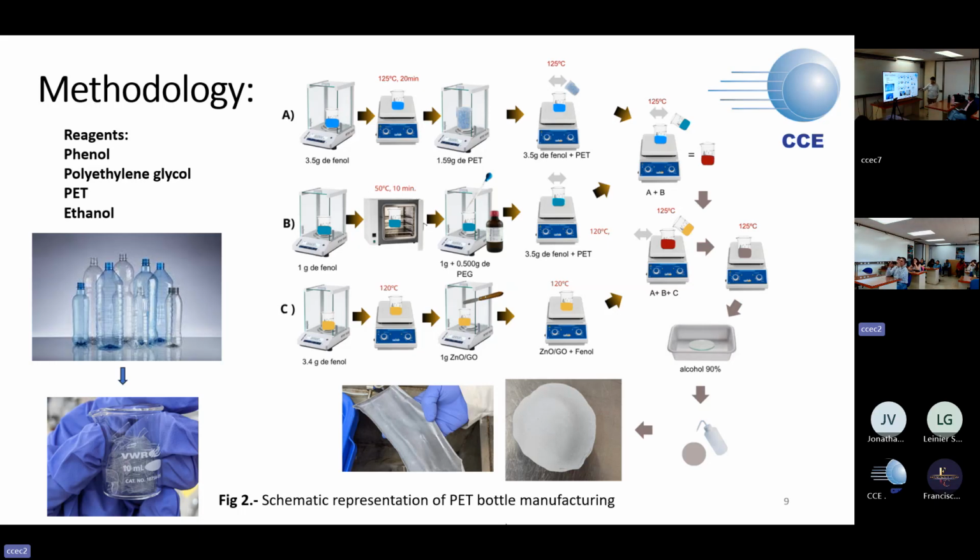In this vessel, we introduce a glass like this one, because it is very flat. So at the end, we introduce all the solution in the glass, and we add before some ethanol in order to facilitate the removal of the membrane from the glass. The ethanol is evaporated by itself.